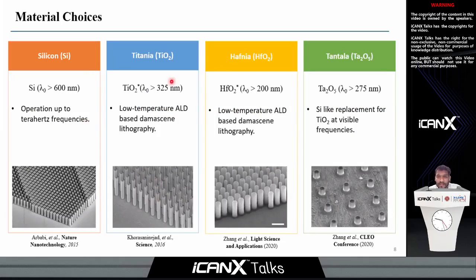And really, I want to stress this material, hafnia, that enables operation down to the deep UV wavelength regime. If I go to a Thorlabs catalog and try to find an objective that works down to, say, 200, 210 nanometers, it's just impossible to find. And if you are so lucky to find one, it is probably going to cost you $20,000. So the metasurface platform based on, say, hafnia is quite strong in terms of pushing the response down to deep UV. But a lot of other groups have shown that you can do very impressive stuff in the visible frequencies with, say, TiO2 metasurfaces, and then silicon is of course the workhorse for operation from, let's say, the near IR spectral range all the way up to the terahertz. So it's quite a remarkable set of material platform choices that are available.